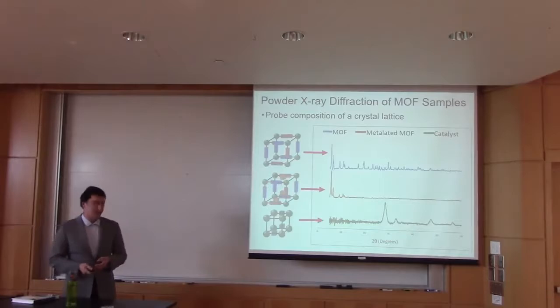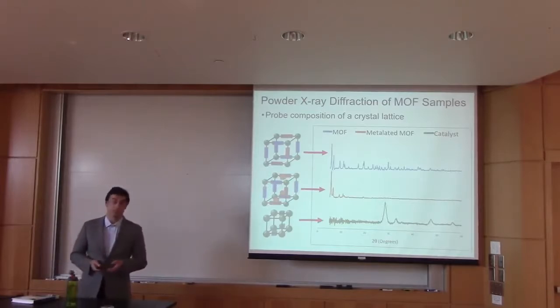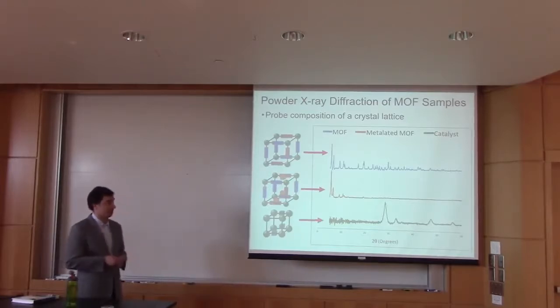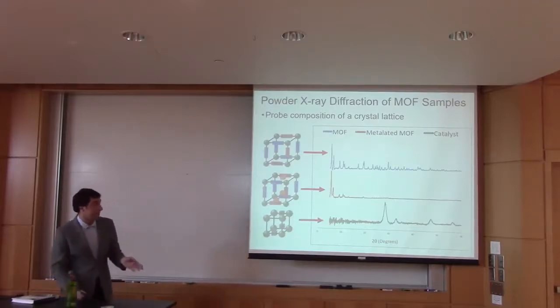And then finally, the pyrolysis looks very different because we've removed a lot of the structure to this MOF, but we still have some crystallinity and some pattern, and this is okay.